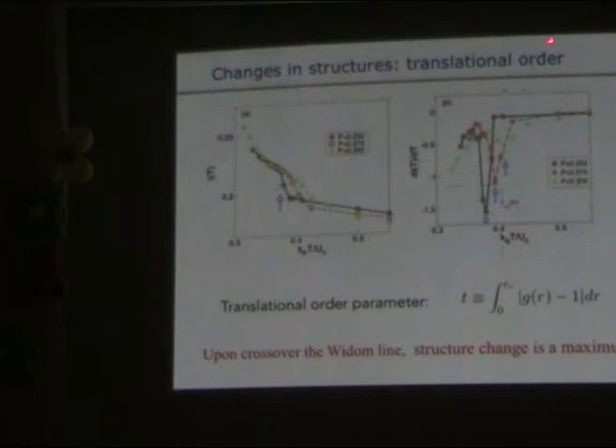And finally, we will give you another example about the response function. It's called the translational order. Before, I showed you how this system is locally oriented, and this is a long-range order. If there's a long-range order, you can get this parameter really different from the other one. You can see that as you decrease the pressure, this is really far above the critical point, this is in the middle, and this is quite close to the critical point. You can see the translational order also shows some indication.